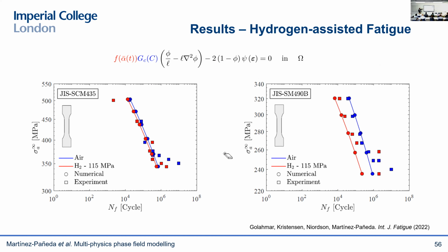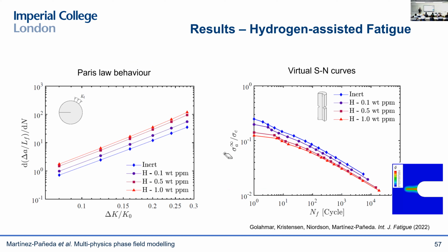So you can see here virtual S-N curves where we can predict, I think in close agreement with experiments, both the predictions in the absence of hydrogen and incorporating hydrogen. And these are cycle by cycle calculations, which means that they're computationally heavy, but at the same time, they're very powerful in that we don't need to make any prior assumptions. We can predict the Paris law behavior as an output of the model, not as an input. We can predict, therefore, the role of hydrogen in accelerating fatigue growth rates, and we can deliver virtual S-N curves for any arbitrary choice of loading conditions, loading history, geometry. You can see this is for a notched bar. So I think this is computationally quite compelling and quite an interesting area to explore.